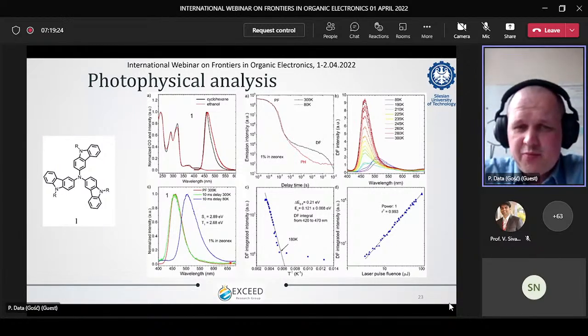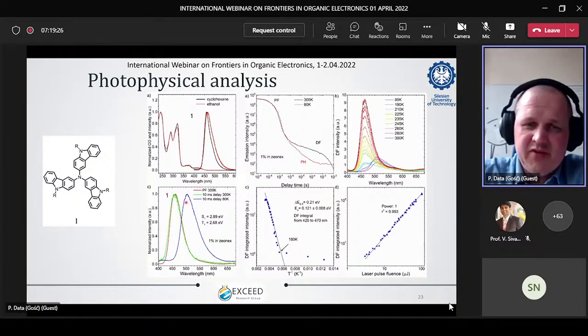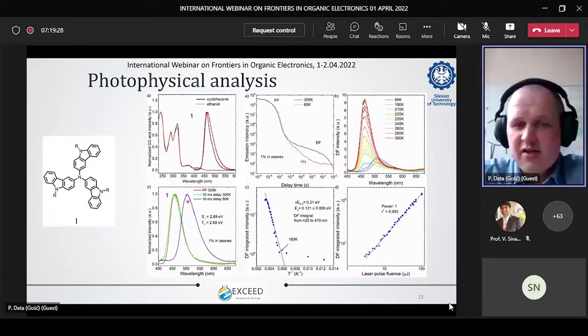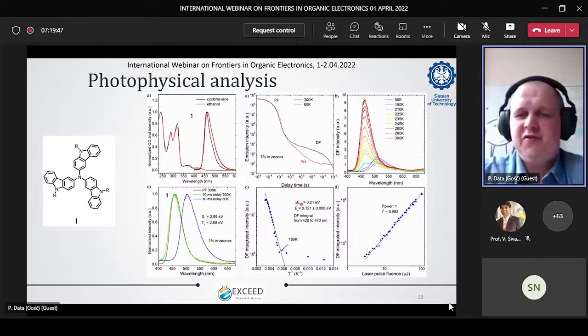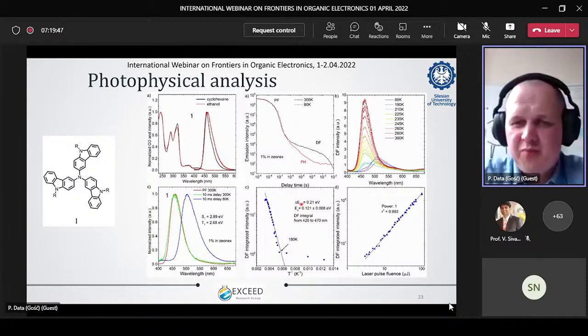And they had similar emissive properties as the ambipolar one, but they were only donor molecules. Another important factor which you should know: we always explain our ST gap, the energy difference between singlet and triplet level, and this is good for screening.